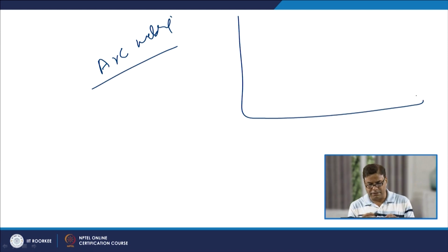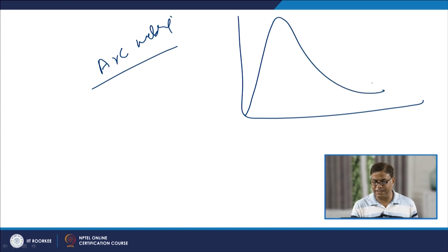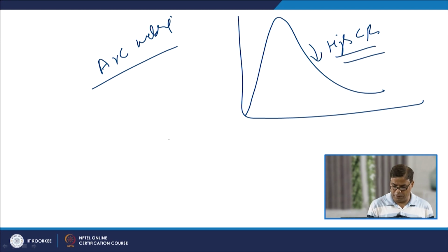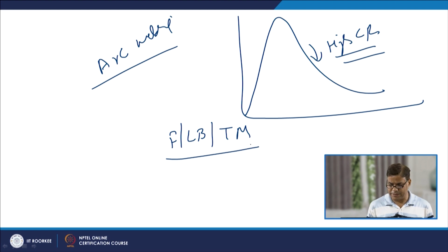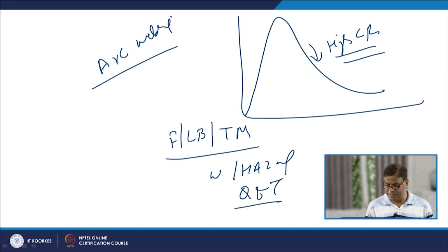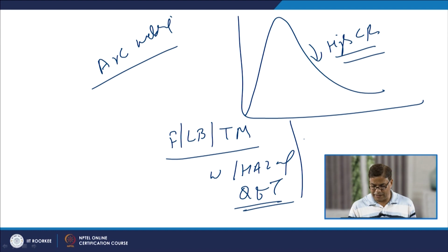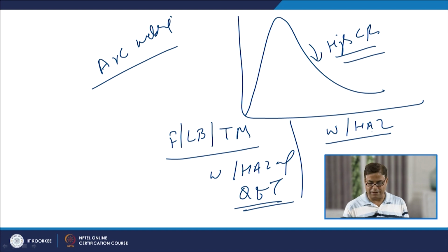Otherwise, in most of the arc welding processes, the kind of weld thermal cycle which is realized in the weld as well as the heat affected zone is such that the cooling rate is high enough to form ferrite, lower bainite, and tempered martensite, auto tempered martensite, in the weld as well as the heat affected zone of the Q&T steel weldments, and that is why the mechanical properties of the weld as well as the HAZ of the Q&T steels are similar to that of the base metal.